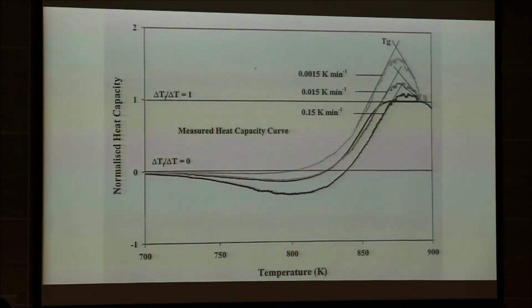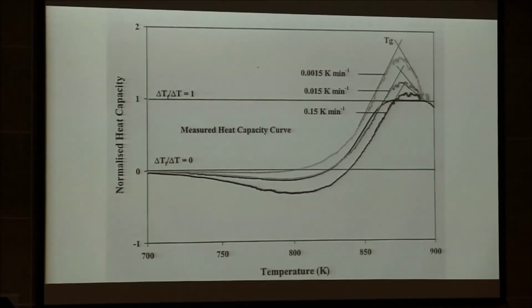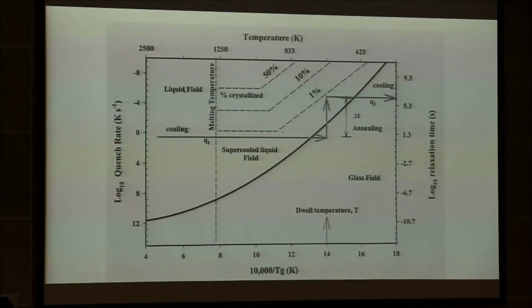You can get it on the edge of pillow lava erupted into water. You can get it in explosive scenarios where the glass is fragmented into very small parts. But if you go outside of this building and walk across a basaltic lava flow somewhere here, you're probably looking at something which is virtually completely crystallized. Nevertheless, if you scratch and stare long enough, you can find glass. And here we determine a few glass transitions for basaltic glasses. You see that they are cooled here at relatively slow cooling rates, so it's remarkable that these glasses are preserved.